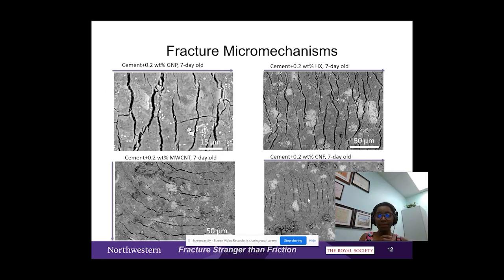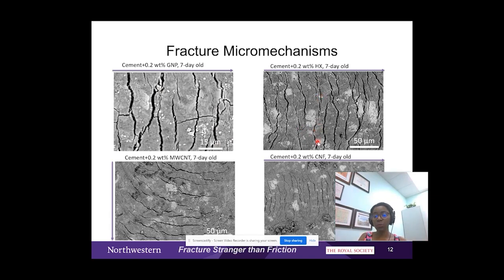So after conducting my scratch test, I then use a scanning electron microscope to image the residual groove after scratch testing. One thing that I noticed was the presence of microfracture on the surface of those residual grooves, and those fracture surfaces were perpendicular to the direction of scratch testing. This means that during scratch test, we are activating fracture processes, and therefore we can use the test to be able to probe the fracture resistance.